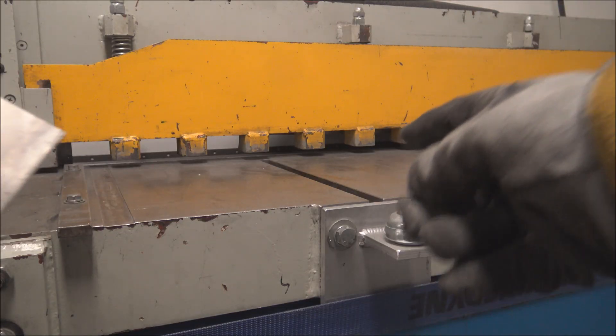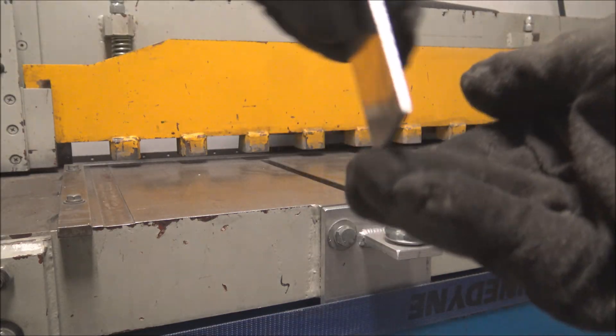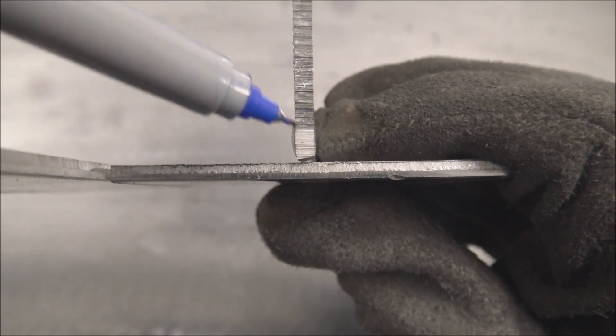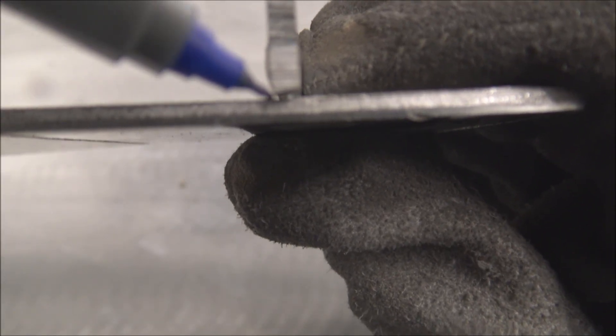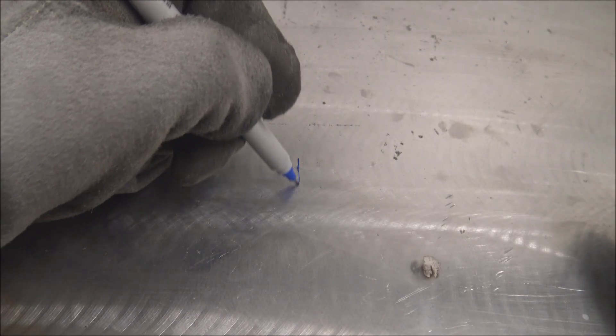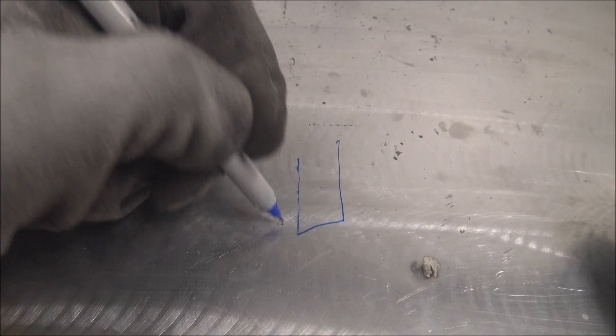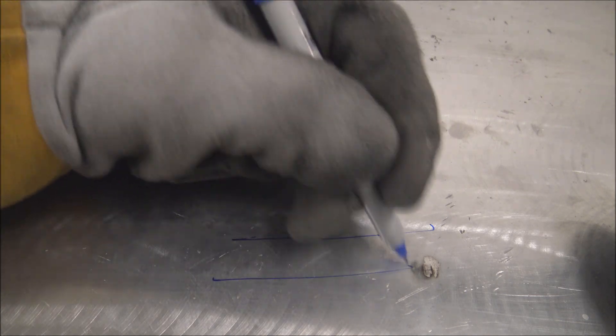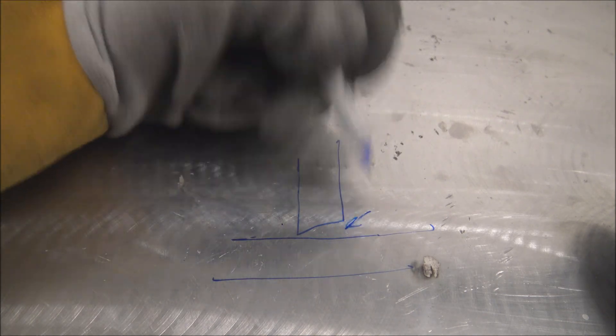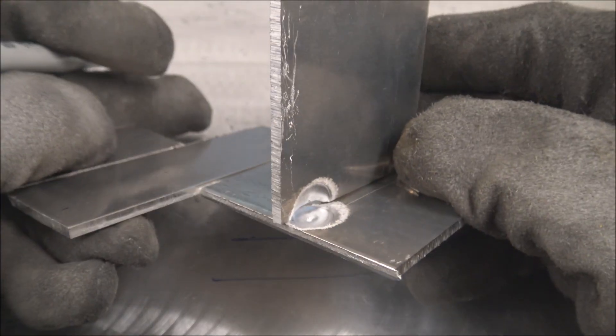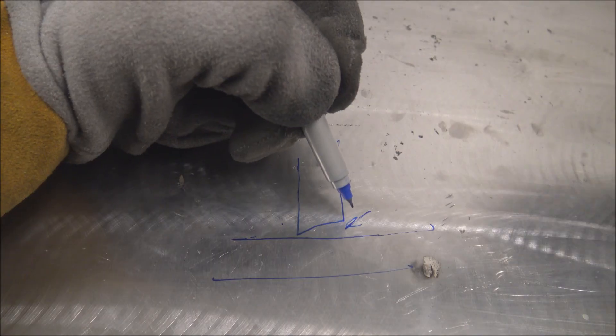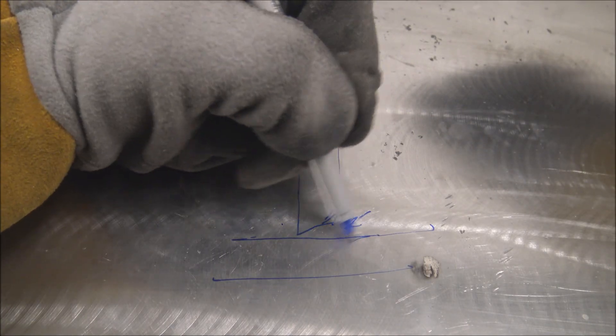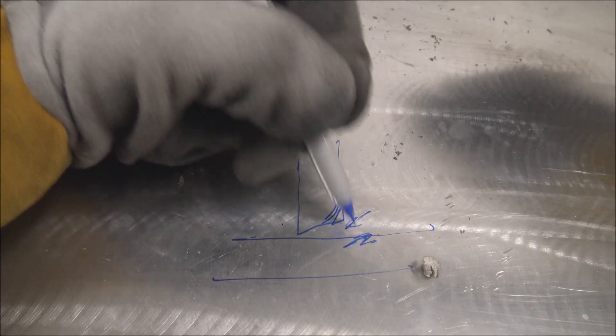The problem with shears when you're cutting parts to fit and tack weld them is that the shear doesn't cut them perfectly square. If you look close, you can see how this left hand side is lower than the right hand side. When you cut it, it does like that. Then if you're putting that on as a T-weld like I showed you where it wouldn't tack, I came in from this side to try to tack weld it. Since over here it's not touching, it is a lot more difficult to get it to fuse. This burns back and this burns away so they don't touch.